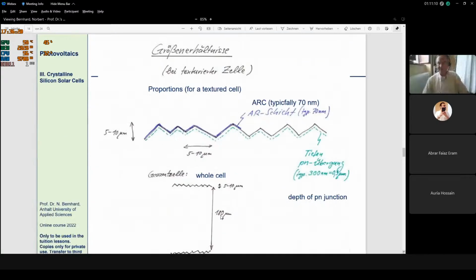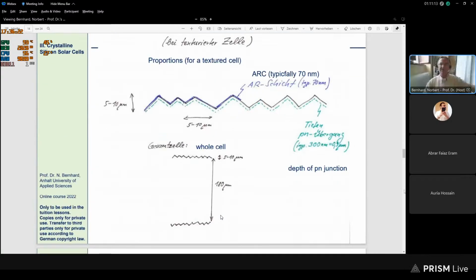Okay, let's now recall the proportions of the cell. You see, I have drawn here the surface of such a textured cell. The total cell thickness, the whole cell would be this one. It's roughly 180 micrometers thick. This textured region is 5 to 10 micrometers. That means the height of these pyramids in this case is 5 to 10 micrometers. And then you see the PN junction, which is a dashed green line. It precisely follows this texturing. So that means this is a PN junction.